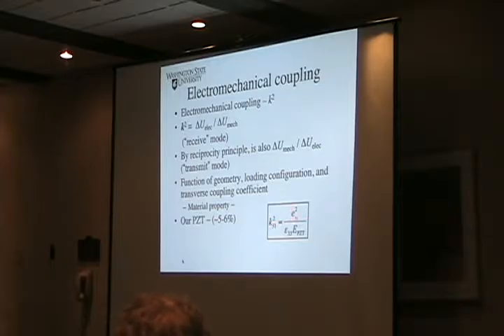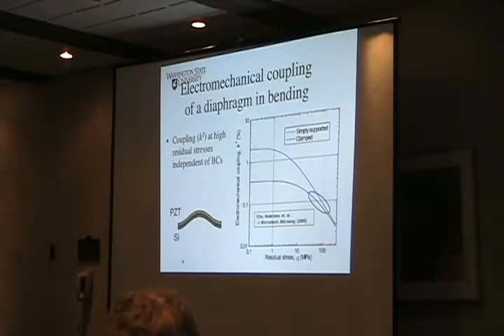First off, and we're not the first people to point this out, there are quite a few people. Paul Morrell used a figure of merit to define efficiency and power generation, which was piezoelectric constant squared divided by dielectric constant. We threw in moduli just to make it a little bit easier for us to work with. And so we see we have our piezoelectric coefficient, our dielectric coefficient. We can change these properties through doping and some other things about processing. That's a lot harder to change, so we're not going to change it. We said, okay, well, that's as good as we can get for a stretching membrane.